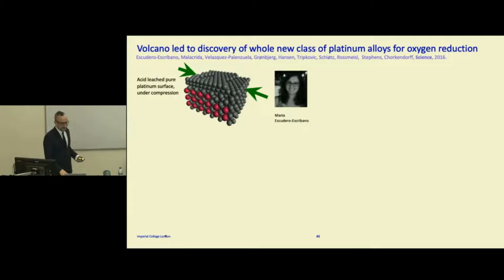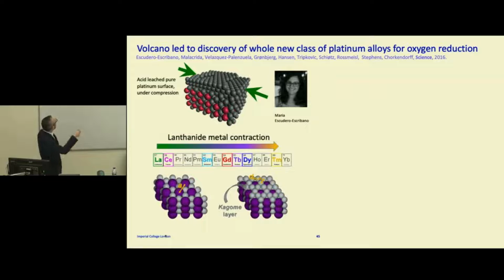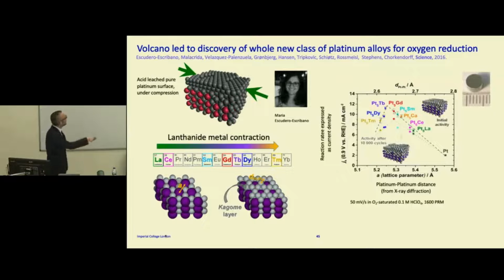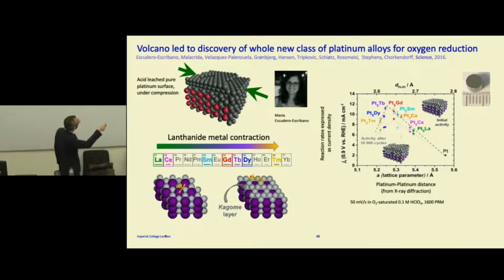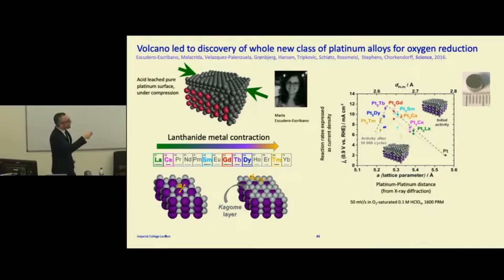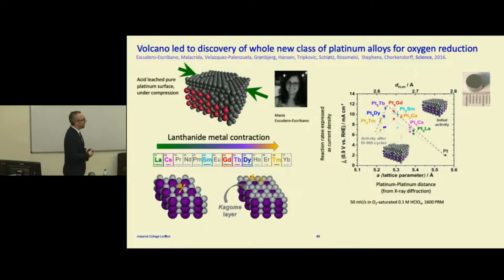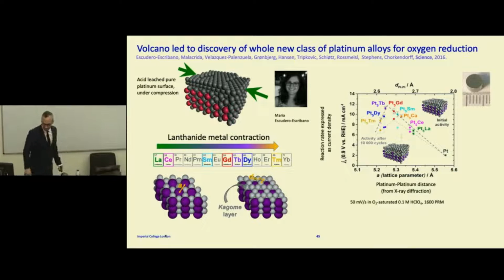The nice thing with the lanthanides is they have quite a boring chemistry, all the same. The only thing you're changing is the size of the atom. So we think that the activity is controlled by the platinum-platinum distance at the surface. That means we should be able to reach optimal activity by just changing the lanthanides. And this is exactly what we did. We've got another volcano here, and we've got extremely high activity. A good thing about this is that, in principle, in a fuel cell, you could get away with using about 5 times less platinum. So you could scale up fuel cells more easily.